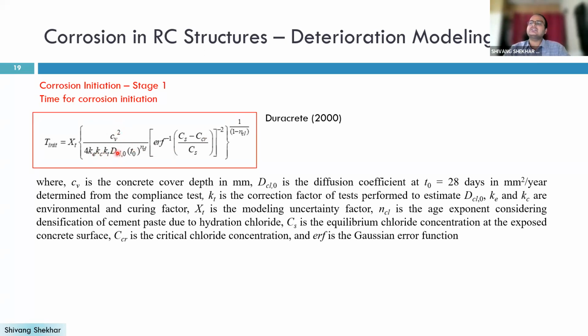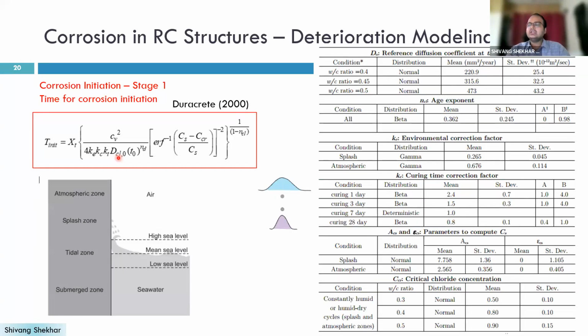Basically, these equations are developed based on lab tests. So they put in some kind of environmental correction factors like Ke, Kc, and Kt, and obviously there is the diffusion coefficient. The higher the diffusion coefficient, the earlier the initiation time of the corrosion. In this document, and obviously several other researchers who work directly on corrosion based on the exposure scenario, like atmospheric, marine splash or tidal, or submerged zone, have given the parameters for this.